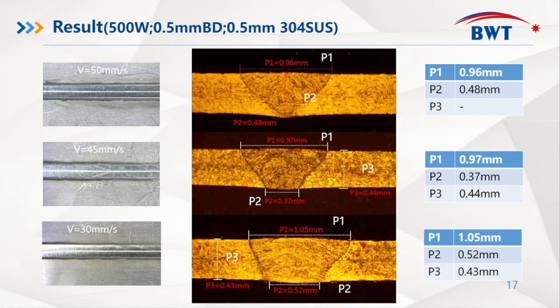Using 500 watts power to weld 0.5 mm stainless steel plate at different speeds, the speed of 50 mm per second cannot penetrate. Under 30 mm per second, the width of the weld bead on the top surface is 1.05 mm. The bottom width of the weld bead is 0.52 mm, and the actual thickness of the stainless steel plate is 0.43 mm.